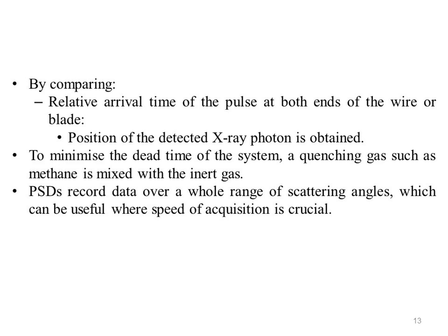Such a detector can process many events concurrently. PSDs record data over a whole range of scattering angles, which can be useful where speed of acquisition is crucial. For example, in time resolved powder diffraction or thermodiffractometry.